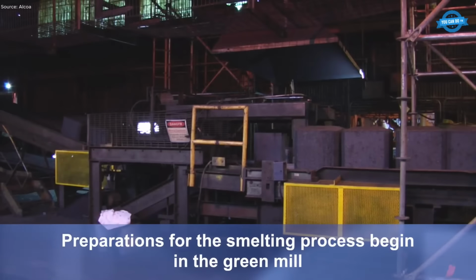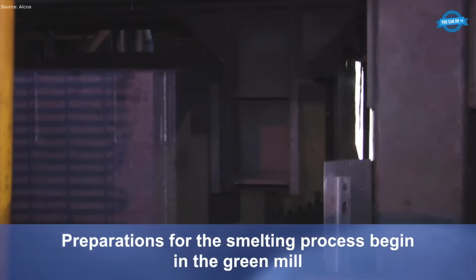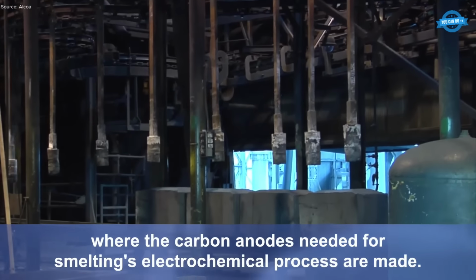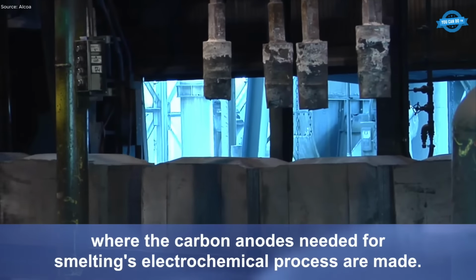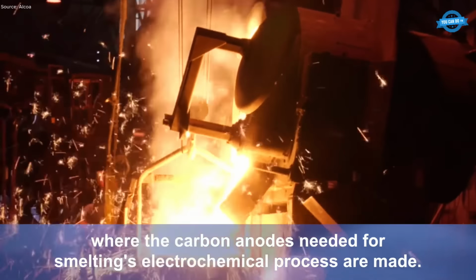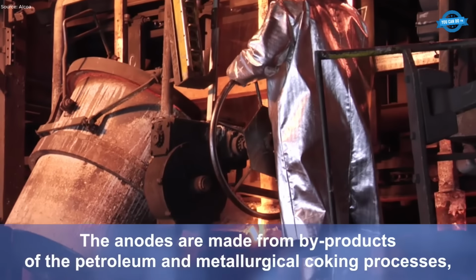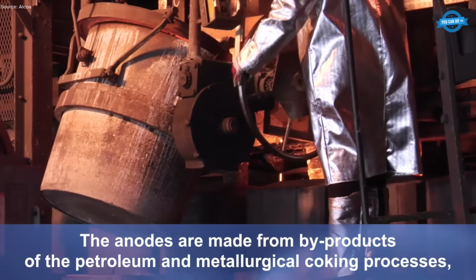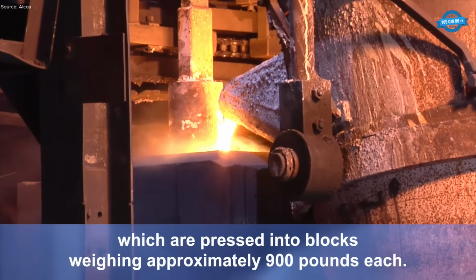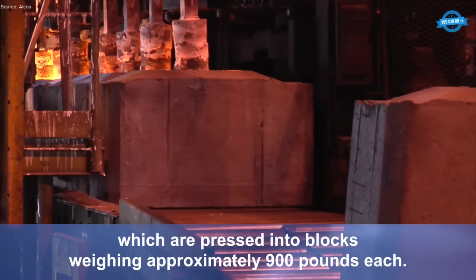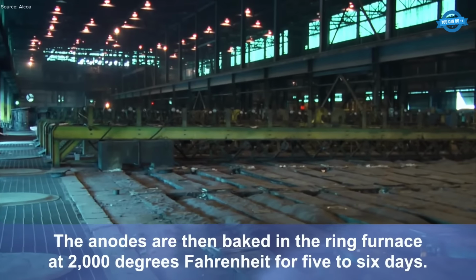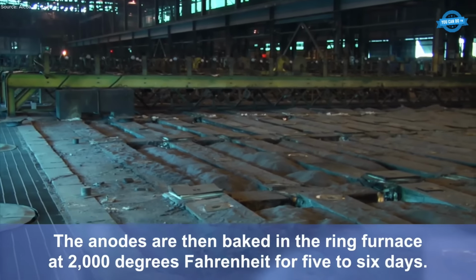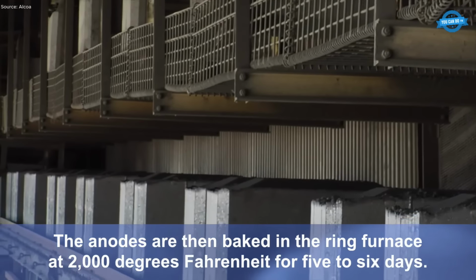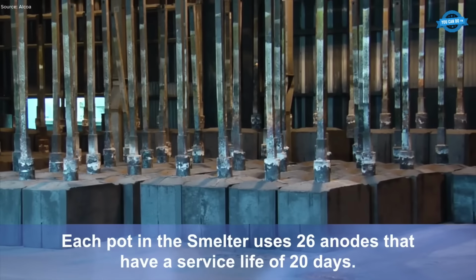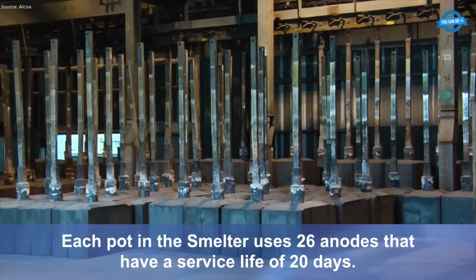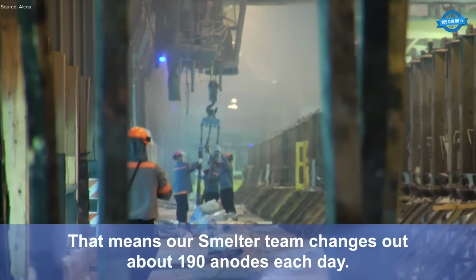The Alcoa smelting process begins in the green mill, where carbon anodes are manufactured from petroleum and metallurgical byproducts. Each anode, weighing around 900 pounds, is baked in a ring furnace at 2000 degrees Fahrenheit for up to 6 days. In the smelter, each pot operates with 26 anodes, which have a 20-day service life. With 150 pots per room and 5 pot lines in operation, the scale is immense.